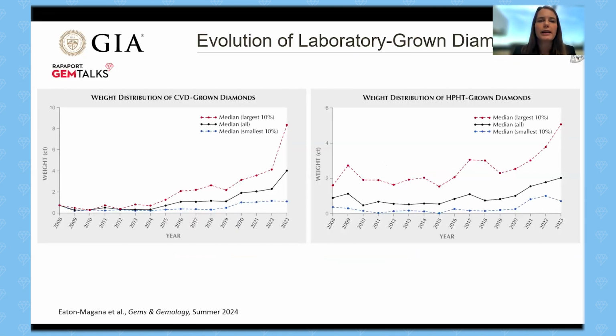And this is really just tracking the evolution of laboratory-grown diamonds as they're coming through at the GIA lab. So you can see here very dramatically that the sizes for the CVD grown and the HPHT grown have been increasing dramatically over the years. Nowadays, for CVD, most of the samples that we see are larger than 3 carats in size, whereas those produced by HPHT are greater than 2 carats in size. So that obviously within the gem trade is a significant size.